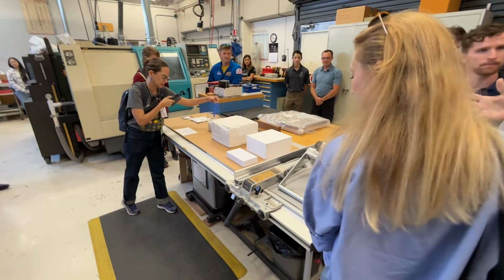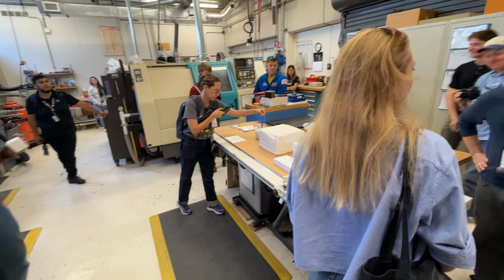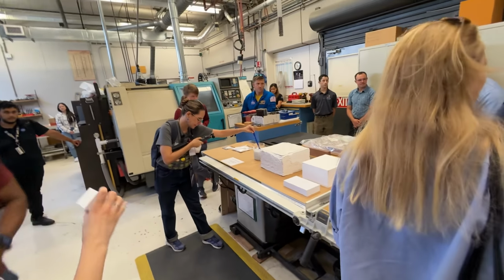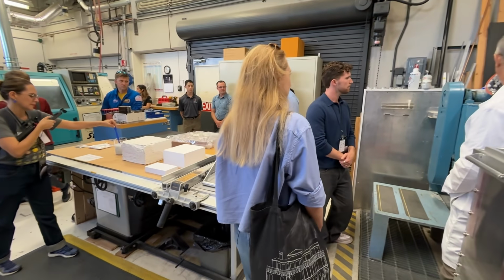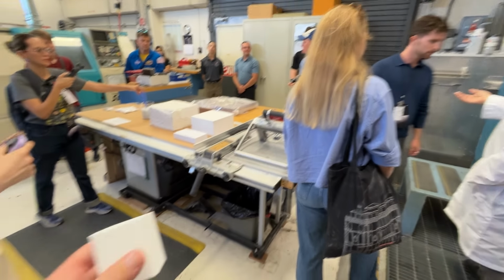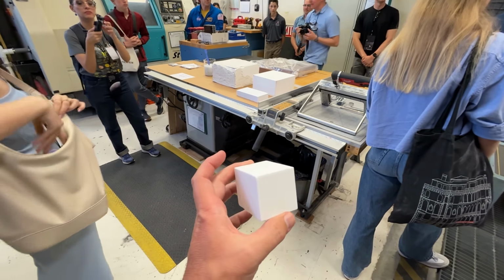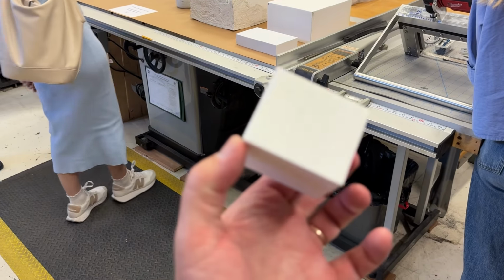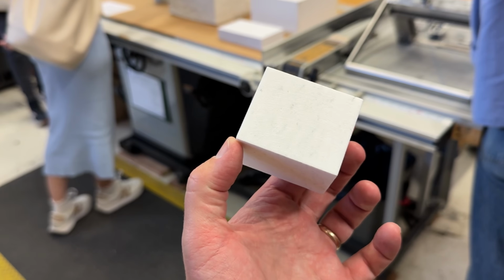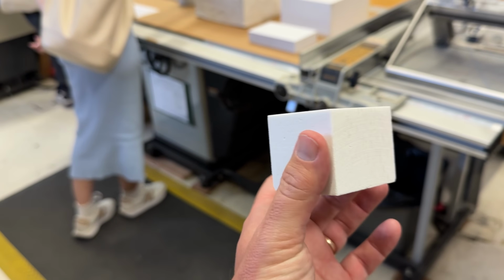But on the lower press, for a lighter press, for say 8 and 12 pound densities, they're more challenging to make. So the fibers start off as what you had in the bags over there. We take a certain amount of those with deionized water and silicon carbide powder, and it goes in the V blender here. And then this is what it looks like after it's been run for about 17 minutes. If you ran it longer, it'd get shorter. Right, it gets shorter and shorter, and the shorter the fibers, the more likely you're only going to make a 20-pound density tile or even greater.